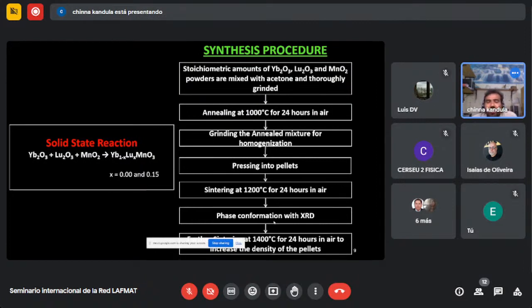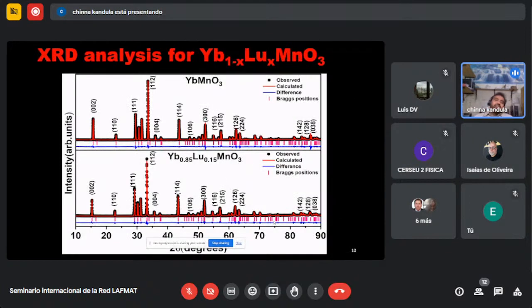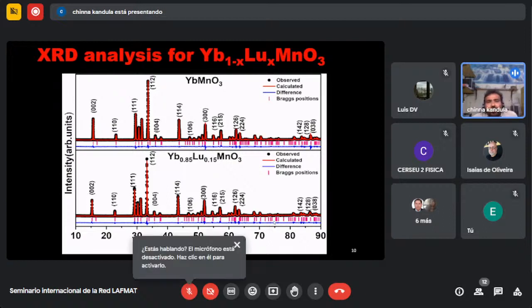Again, for these pellets, I take the XRD. So these are the XRD analyses. Whenever we prepare a sample, we have to check whether that sample is good or not based on XRD only. I know the parent compound's XRD pattern from the literature, so I want to see whether it is formed as a single phase or not.